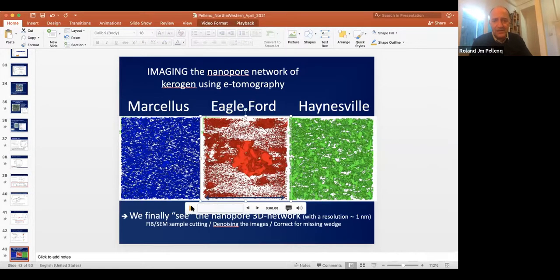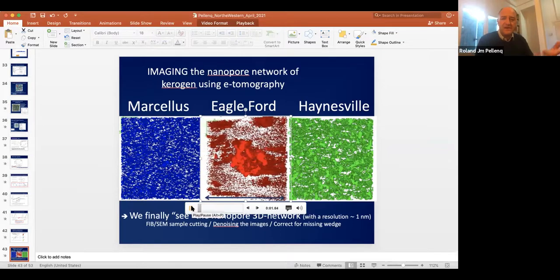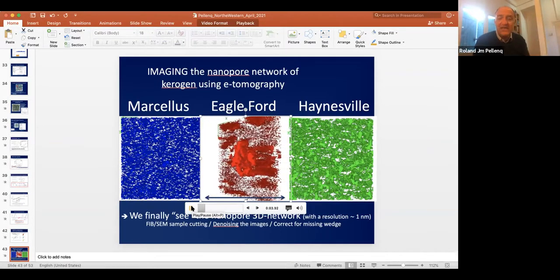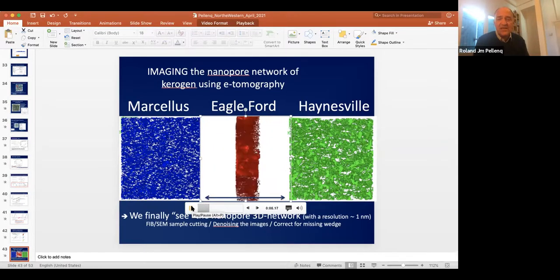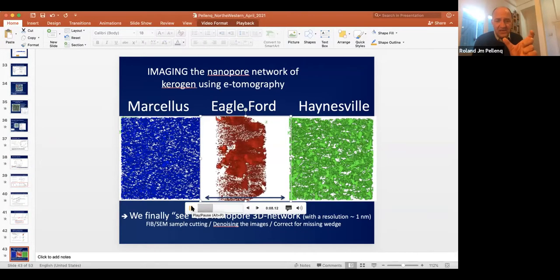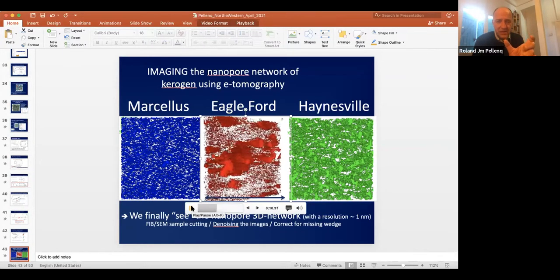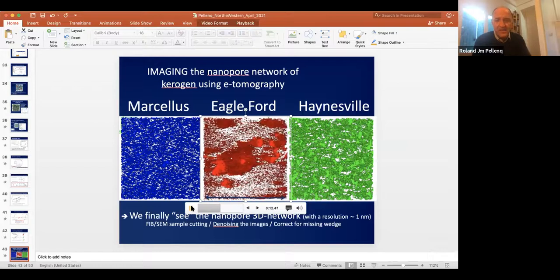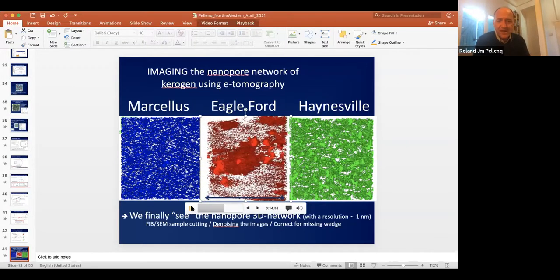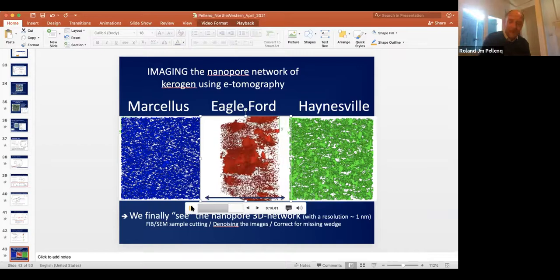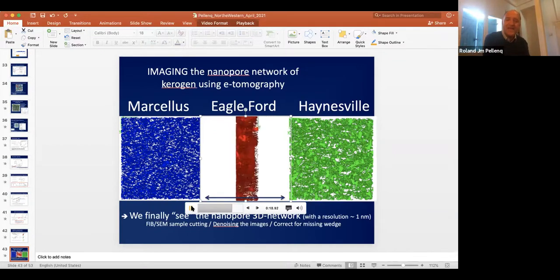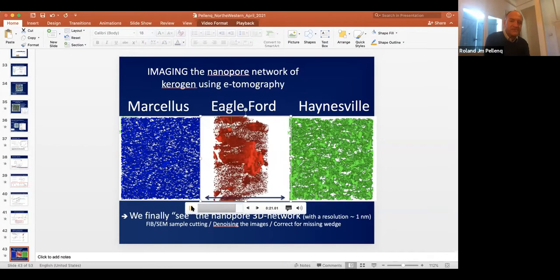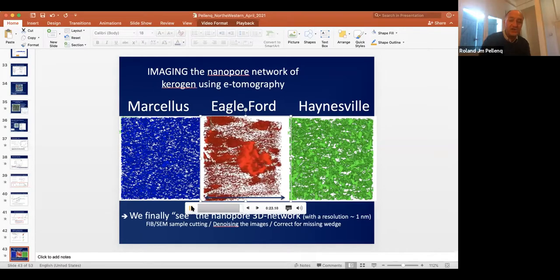So let's do this one, for instance. This is a piece of Kerogen from Eagle Ford, which is a field in the US. You can see that the sample size is 200 nanometers, the size of the box. And you can see a big pore in the center, and the tiny pores that we were studying up to now. Meaning that in those big pores, obviously, we do recover a Darcy behavior.